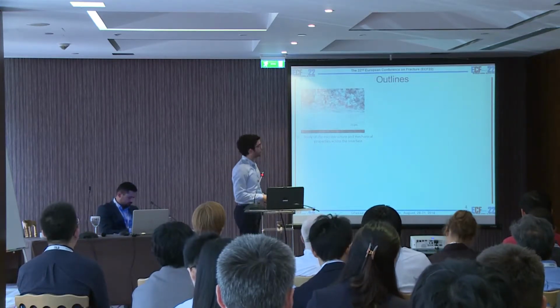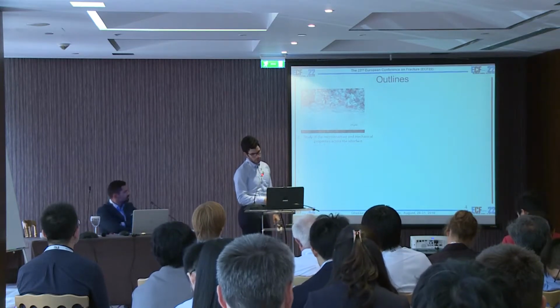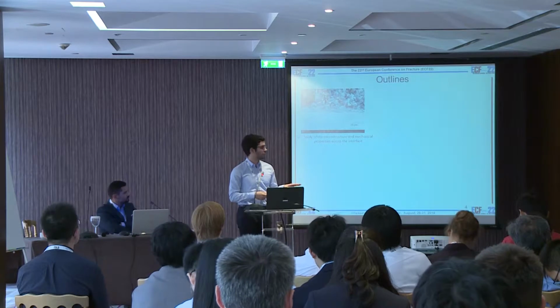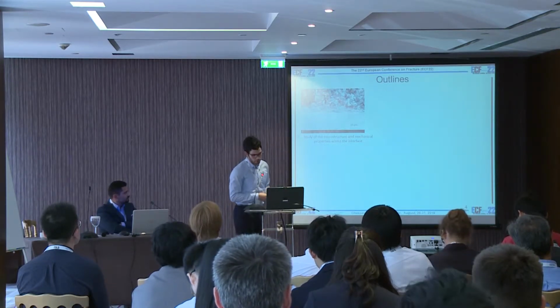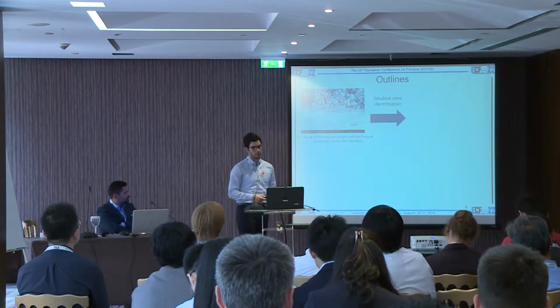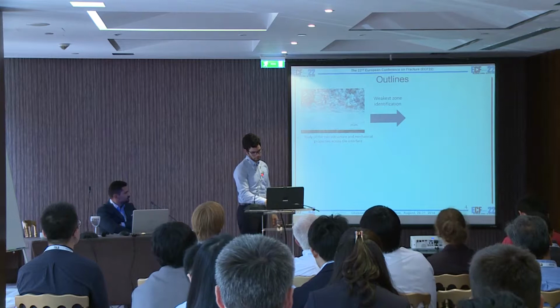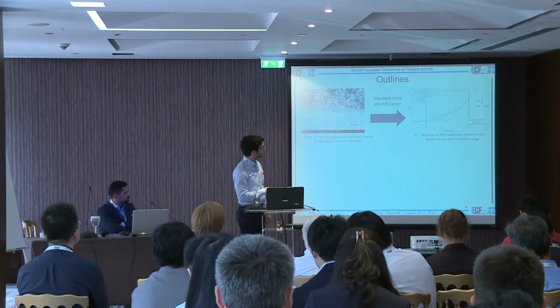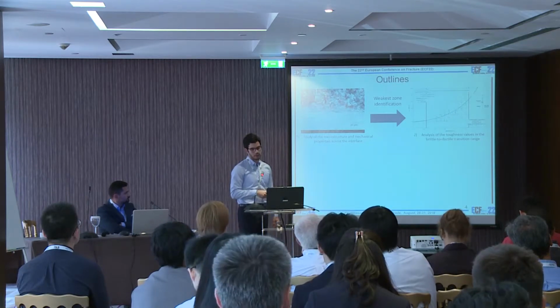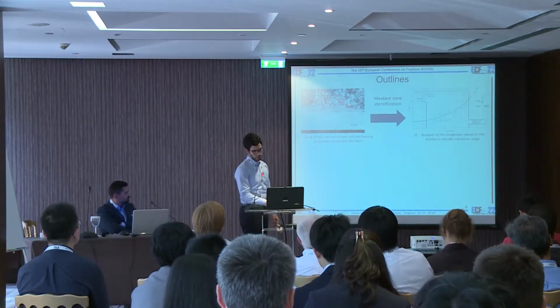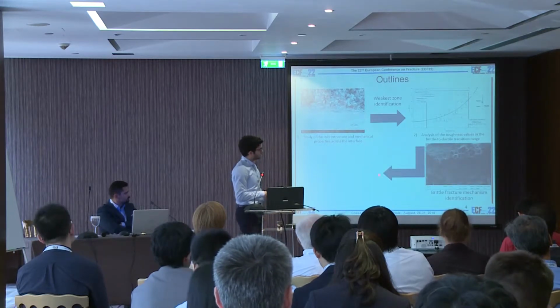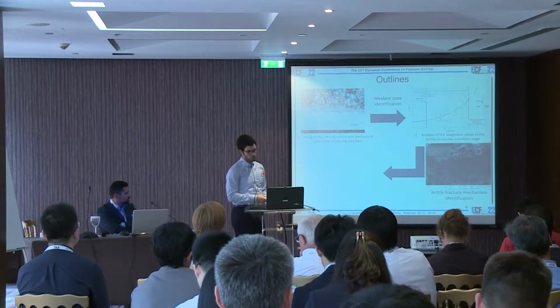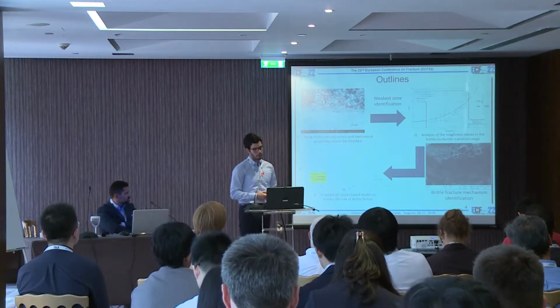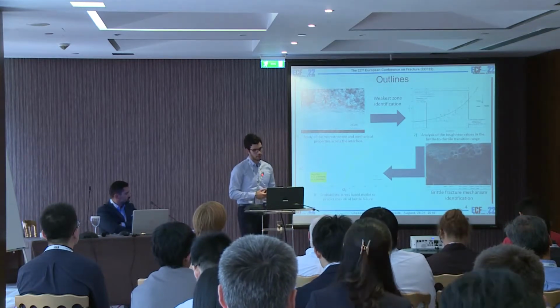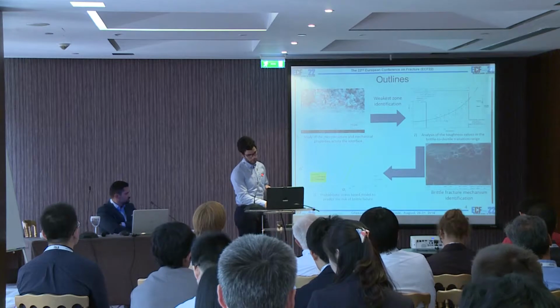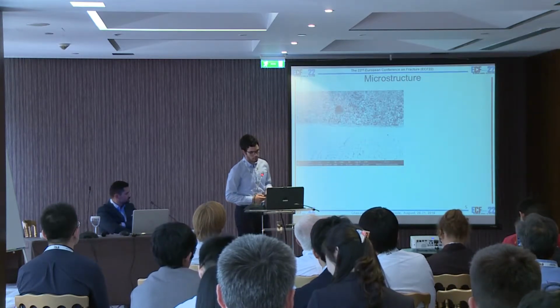To answer that question, here are the outlines of my work. First of all, we start from the microstructure level, and we study the different microstructures across the interface in order to identify the weakest zone for brittle fracture. Then an analysis of the fracture resistance with toughness tests is required in the brittle to ductile transition domain, and we will identify the brittle fracture mechanism which is involved. And then we will try to come up with a probabilistic stress-based model to predict the risk of brittle failure for this SSDMW. So let's start with the microstructure.